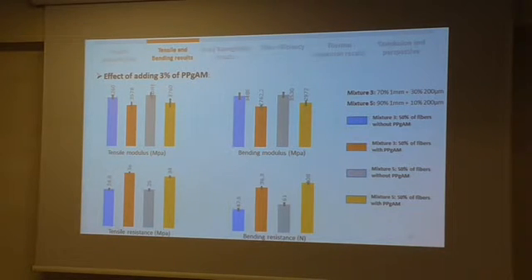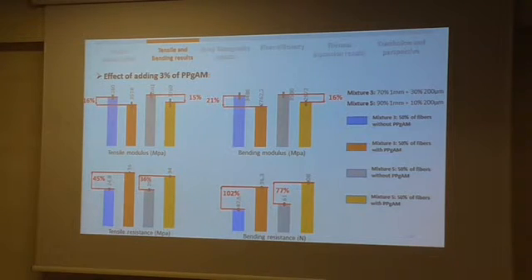We added 3% of PPgAM, which is a compatibilizer, in mixture 3 and mixture 5 with 50% of fiber rate. We noticed that it has a negative effect on the tensile and bending modulus, and a positive effect on the resistance. We noticed a decrease between 15 and 16% in tensile modulus, and between 16 and 21% in bending modulus. For resistance, we noticed an increase between 36% and 45% in tensile, and between 77 and 102% in bending.